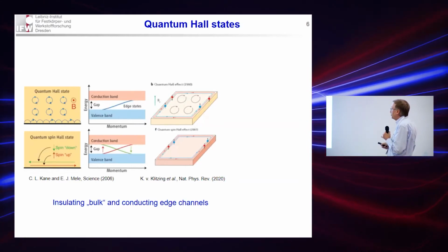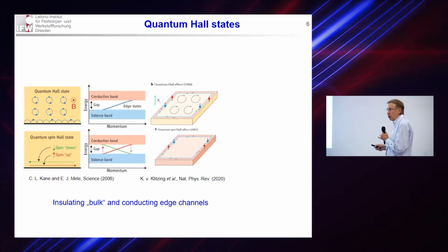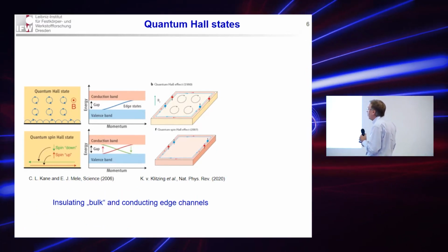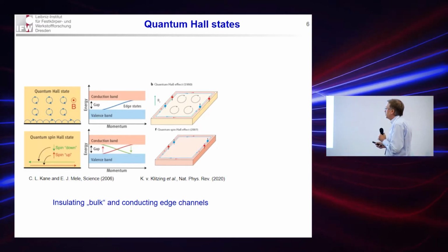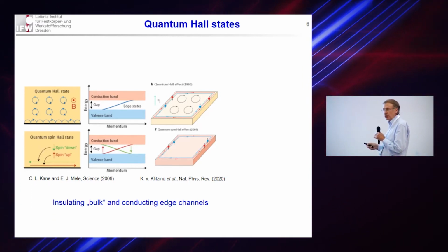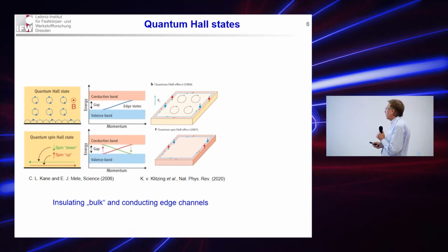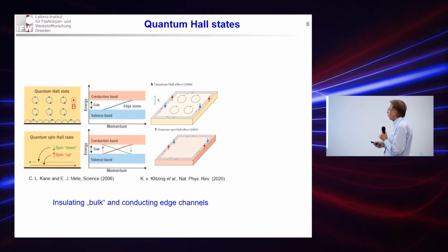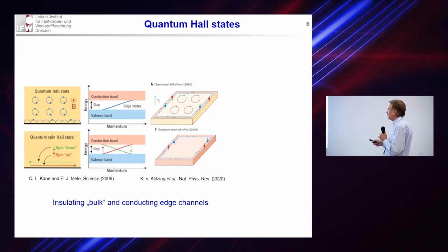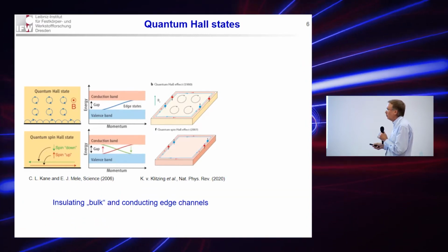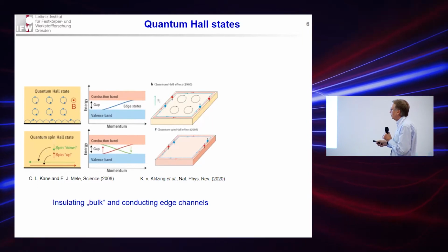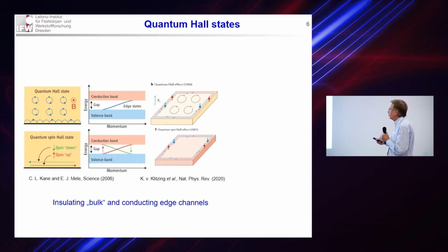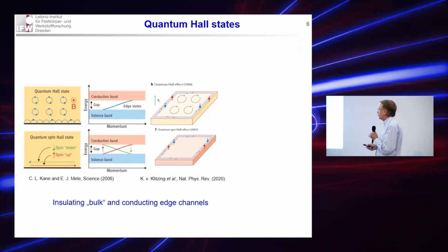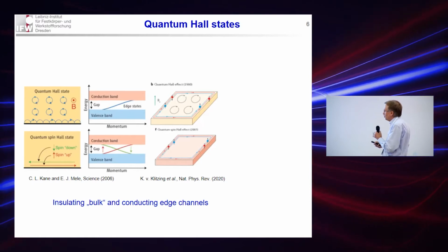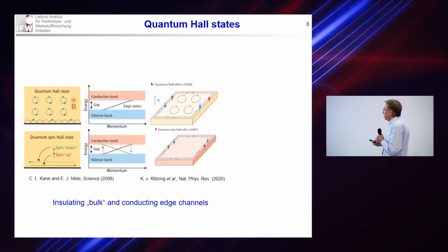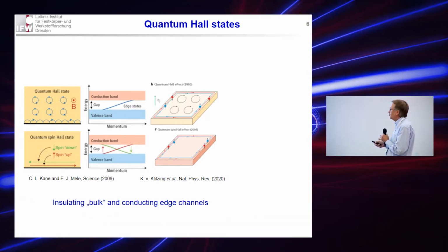However, in a strong magnetic field, the electronic orbits get confined to circular orbits, which are called Landau levels, and so this two-dimensional metallic sheet gets insulating. However, as soon as the orbits touch the interface between this two-dimensional electron gas and, say, vacuum, they start to form chiral orbits, chiral currents, which run along the edges of this two-dimensional electron gas. This is a very interesting phenomenon which was discovered and studied in quite some detail.